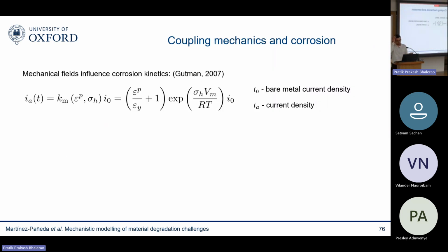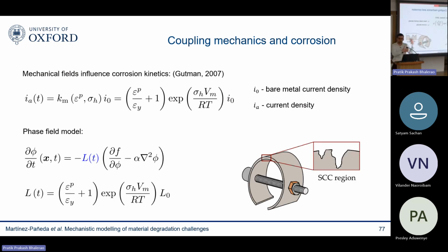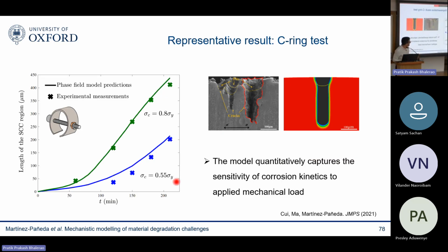And so we try to contribute to this community. I think it's fair to say that we were one of the first groups to do these things. And we were the first to incorporate the role of mechanics. Mechanical fields can enhance corrosion kinetics. We know that there's an expression derived by Gutman. So we can incorporate that into our model by enriching this mobility coefficient, and then we run virtual experiments, and you can see that we get a very good agreement with experiments for 2 different levels of applied load, not only in terms of the degree of corrosion, but also the morphology of the corrosion front. So there's multiple pits in these images on the same scale. We model only one, but it looks to be in good agreement.